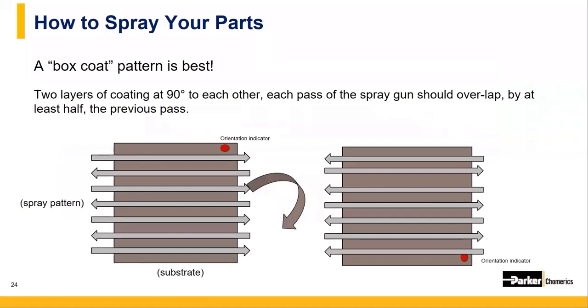Conductive coatings are formulated to be applied via a spray gun, and in most cases, you should not brush these on. The main reason for this is the even distribution of the conductive particle flake technology. So these flakes are meant to lay flat and be present in equal distributions across the entire surface. Each coating should be applied to a specific wet layer thickness, which will eventually dry or cure to a dry film thickness. And in some cases, several thinner wet layers are needed to achieve that correct dry film thickness.